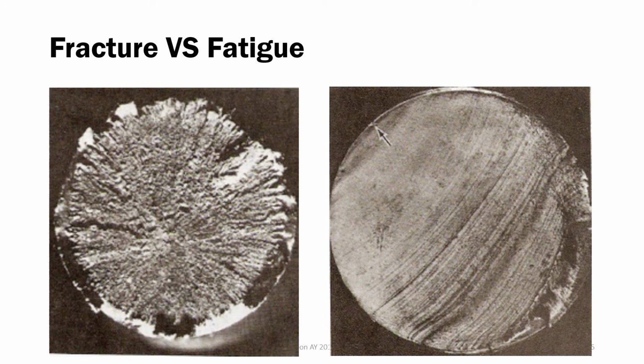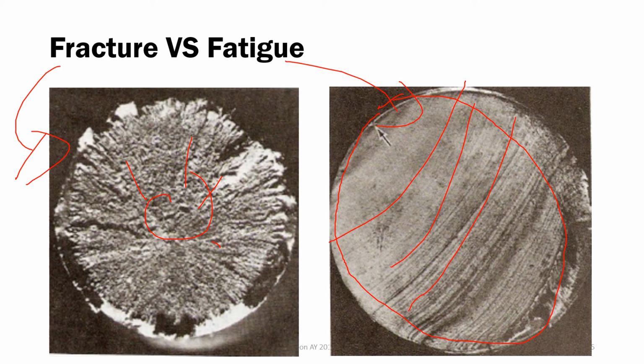So we can differentiate failure by fracture and by fatigue by looking at the fracture surface of your material. If the fracture surface looks something like this, so makita natin yung fibrous zone, radial, and shear lip zone mo, this is usually your fracture na failure. Pag fatigue, your surface is much more smoother. Magkakaroon ka ng mga striations na ganito. So we call those your beach marks. And these usually emanate from one point, usually in the surface or some internal flaw here. So pag ganito yung nakita mo, usually this is a fatigue failure.